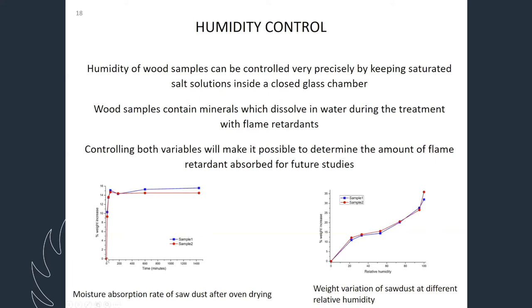Then I took it out and kept it in the open air in our lab. And humidity in our lab is around 33%, quite constant, that I have checked. So within the first 10 minutes, you can see the weight of the wood increases quite fast, almost 15% weight increase. And then I kept it for almost one whole day and the weight did not increase anymore. And I can do this cycle several times. I put the wood back in the oven at 100 degrees. Within 1 hour, it dropped 15%, and when I take it out, within 10 minutes it goes back. So that showed us the amount of residual moisture in the wood.